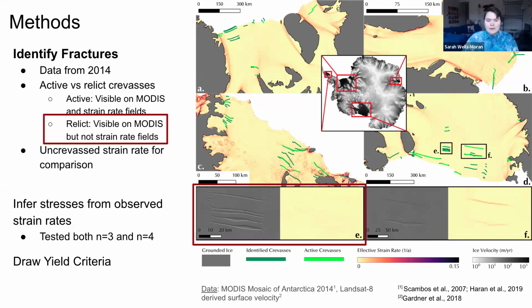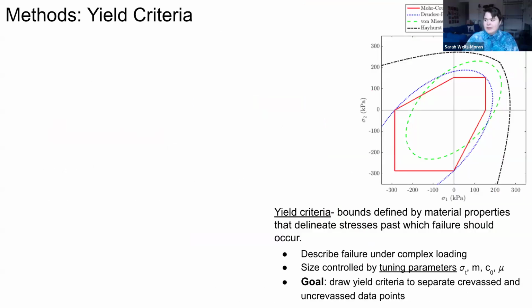So after we infer stress states, we tested for both n equals 3 and n equals 4. The next step is to look at the yield criteria. Yield criteria are bounds defined by material properties that delineate stresses past which failure should occur. And in this situation, we're describing failure as creating a new surface. We're not really distinguishing between brittle and ductile failure.